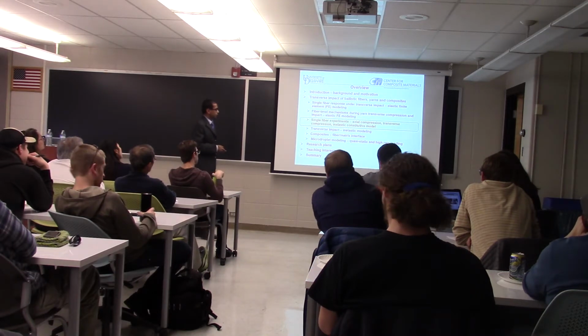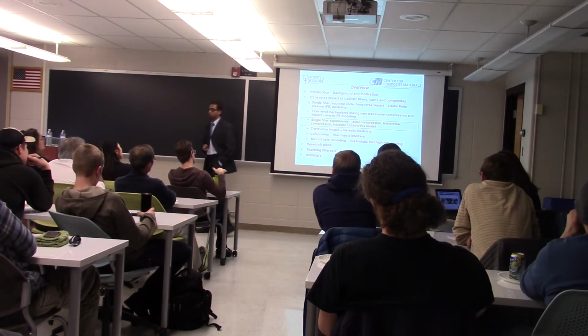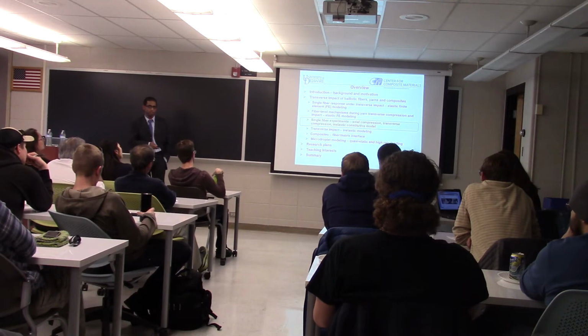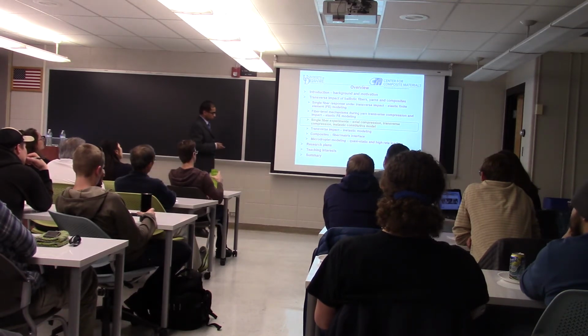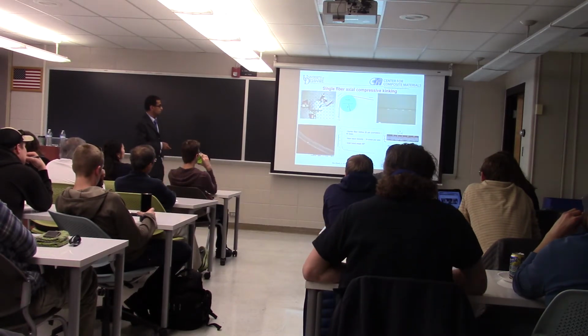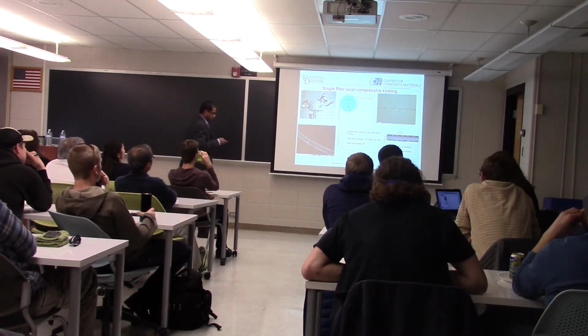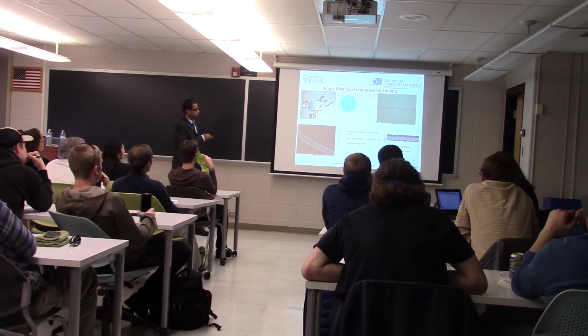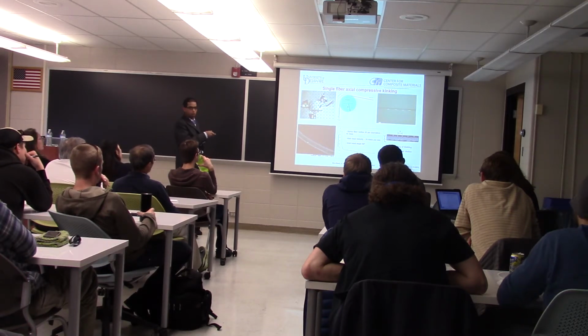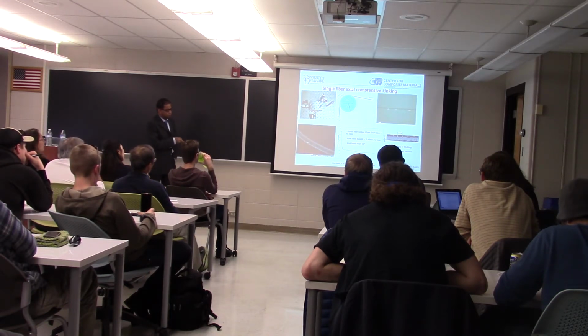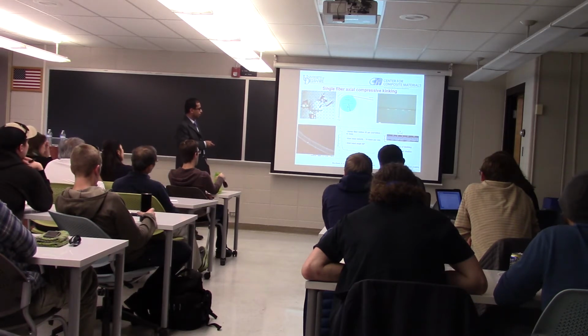So now with these computations, we have some idea of the mechanisms that occur at the fiber length scales. We now wanted to develop some single fiber experiments to better characterize these fibers. So what we did here is, we physically induced the curvature that the model predicts, the curvature from the flexural wave, by wrapping individual single fibers around a boron rod. So by this, we are forming kink bands on these fibers. And we are able to characterize the kink band density and kink band angle.